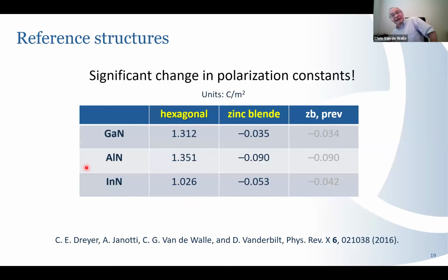Now, I think I already hear some of you thinking, well, why hasn't anybody noticed this? Okay, so let me try and address this. I told you that the spontaneous polarization values calculated for the hexagonal reference structure are very different from the ones for zinc blende. The example of aluminum nitride is what I showed, 1.35 referenced to hexagonal, minus 0.09 referenced to zinc blende. Okay, so these are huge differences, and this is true for each of the nitrides.